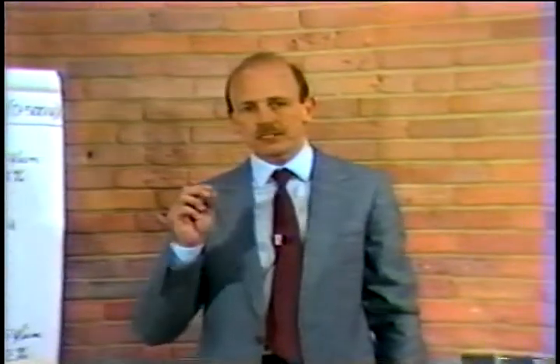Here we plot the change in capacitance that occurs due to partial discharges as a function of time on life test. The partial discharges erode the dielectric material, which then causes a clearing. A clearing removes part of the metal electrode, and this causes a change in capacitance, a reduction in capacitance. Each clearing event removes a very small amount of metal. But yet, when they're all added up, it leads to a very large change in capacitance, as is shown here.